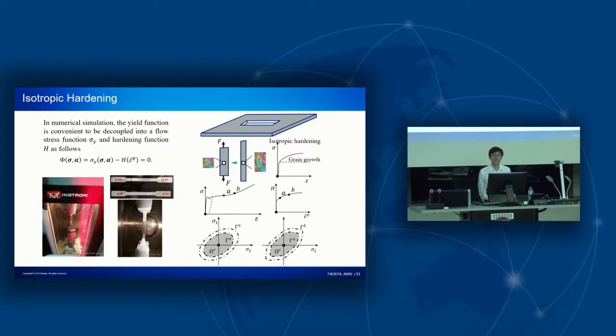Now, people just define the isotropic hardening as the increased size of the yield surface, but no change in the shape of the yield surface. Hence, it's very convenient just to define the yield function as one stress function and a hardening function. The stress function defines the shape of the yield surface, and the hardening function defines the growth of size of the yield surface. To calibrate the material isotropic hardening, we have to perform some standard experimental tests like the uniaxial tension test.